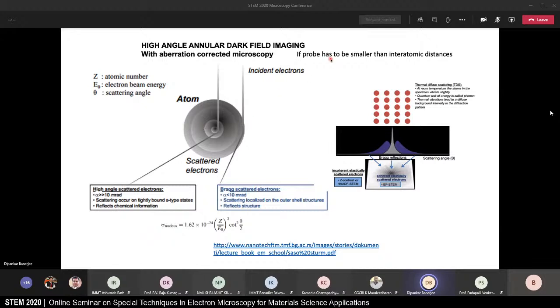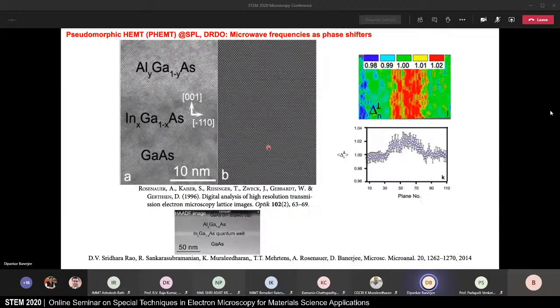If you then make your probe, and you can do this in two ways, your probe size can be varied in modern aberration corrected microscopes, and there are going to be talks about that. But if you make your probes about or smaller than the interatomic distances, then you can image the scattering centers. That is, you can image these atoms because the atoms are the scattering centers. So you can get atomic resolution by scanning the probe over the sample such that you can image the scattering centers at different positions in the sample with atomic resolution. So here are examples of work that Murli and his colleagues did out of DMRL.